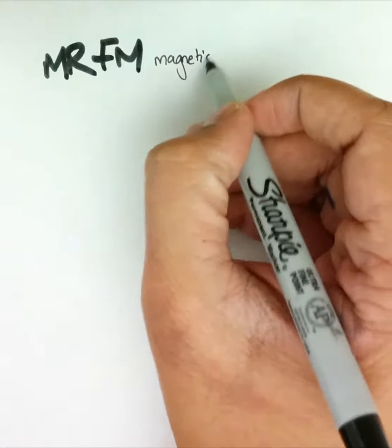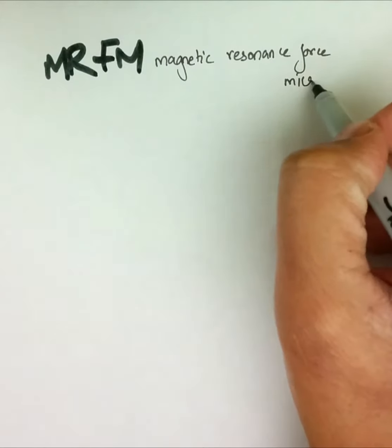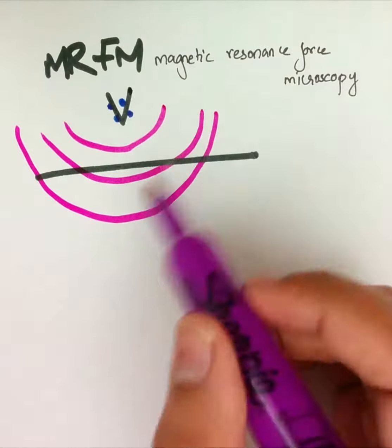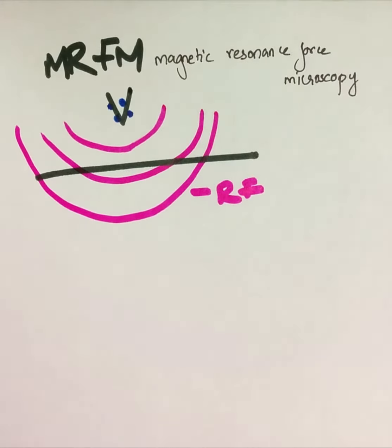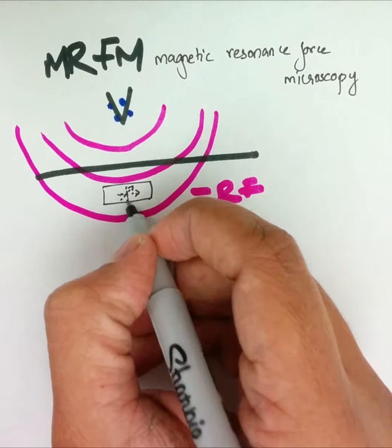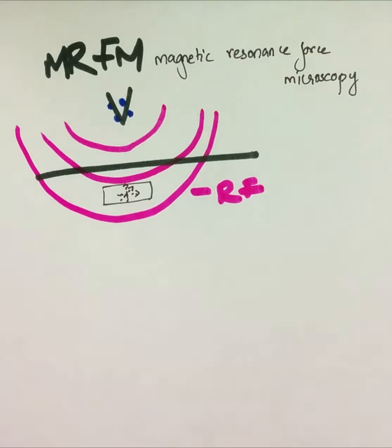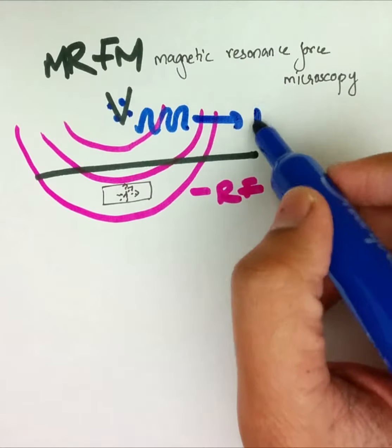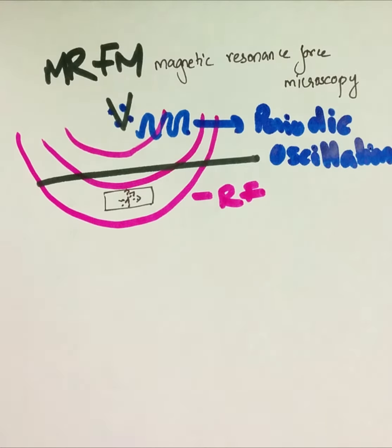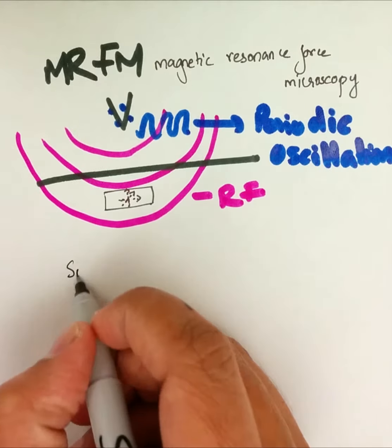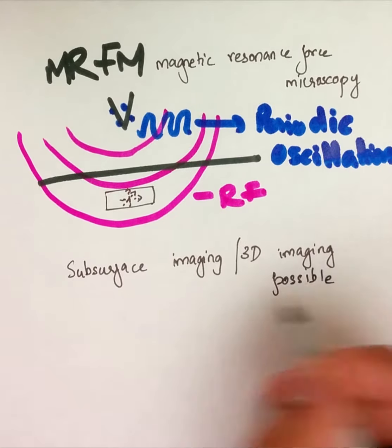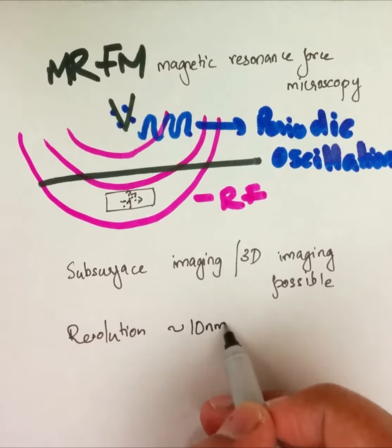Magnetic resonance force microscopy is a technique that combines MRI and MFM. Modulated radio frequency waves are used to invert nuclear spins inside a sample. As the spin configuration changes, it creates a periodic oscillation of the magnetic tip. In some configurations, the tip is kept stationary and the sample is mounted on an ultrasensitive cantilever. The amplitude of oscillation so achieved is on the order of attonewtons and requires specialized instruments to quantify. MRFM enables subsurface imaging and also 3D imaging of the sample.